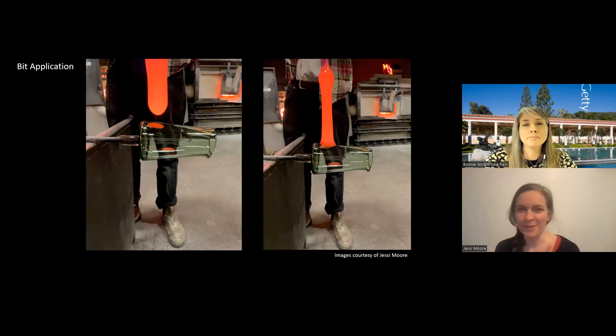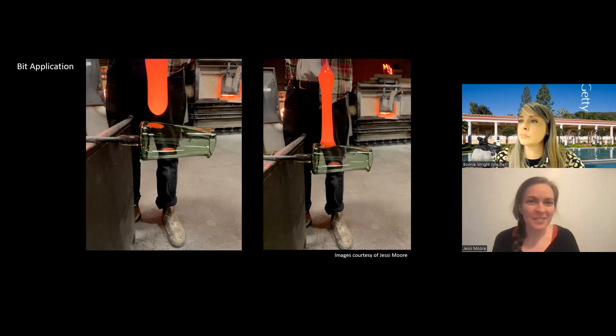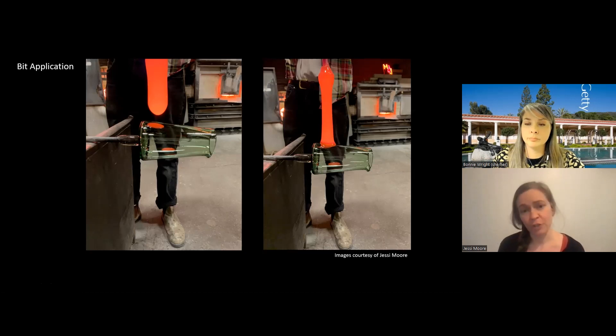I love this little mouse, and those feet on the mouse flask are a really excellent example of a creative use of adding hot bits to glass. This is a really excellent set of images showing the process of adding glass to a pre-existing vessel. Looking at the left slide, there's a pitcher that is basically finished — it still needs a handle. The brighter orange glob aimed at the pitcher is another piece of glass. It's actually the same color — a light body green — but it's much brighter because the handle is much hotter. The pitcher is 'cold,' probably around 1,000 degrees, and the handle is quite a bit hotter and glowing, which means the pitcher will stay in its form while we squish the bit on and pull that bit of glass up.